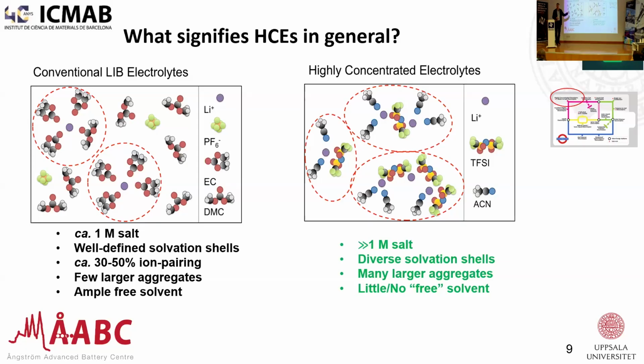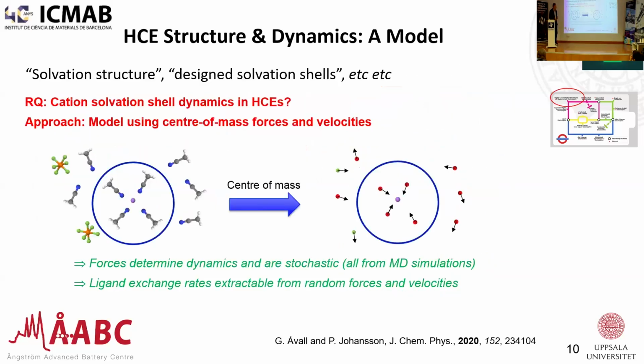But if you go to much higher concentrations, you are really distorting the system now. You get quite a diversification of solvation shells. You can maybe not even define the solvation shells anymore, because everything is interaction with everything. And there is basically very little free solvent, and that's beneficial. But what happens here is, of course, also that you're increasing the salt amount, and that means, in the scale that we saw before with cost, salts are very costly compared to solvents. So this is a high-cost solution, so you have to bring some other benefits to it. But of course, benefit number one here is that you don't have free solvents, so you're improving the safety, right?